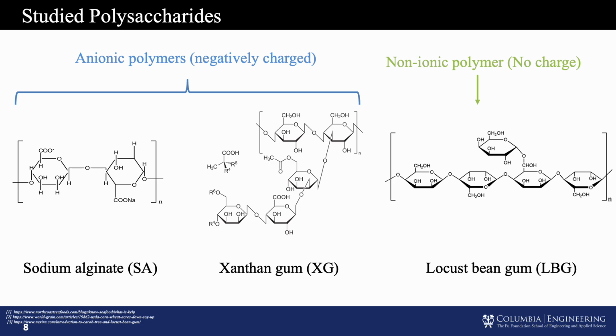As most of the water-soluble polysaccharides are either anionic or non-ionic, today I'm going to introduce two anionic biopolymers and one non-ionic biopolymer to give you an overview of biopolymer-stabilized earthen material. I will specifically introduce what we found in anionic biopolymers' rheology and 3D printability. For the non-ionic biopolymer, unfortunately, I can't present today, but I will quickly show how it affects suspension stability. But for the anionic ones, sodium alginate and xanthan gum, I will specifically show how this micro-level particle interaction affects their rheology, and eventually how this rheology translates to large-scale 3D printing.